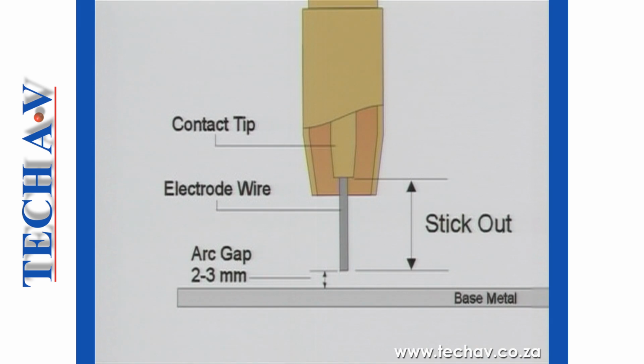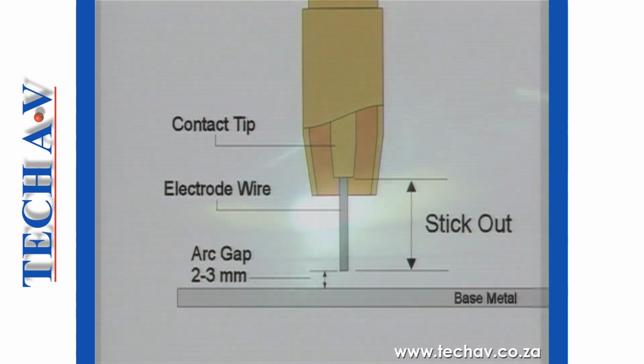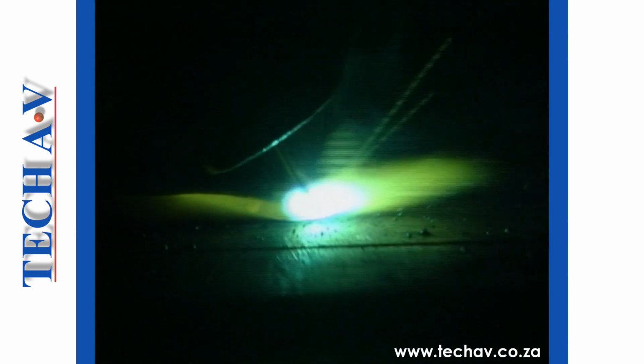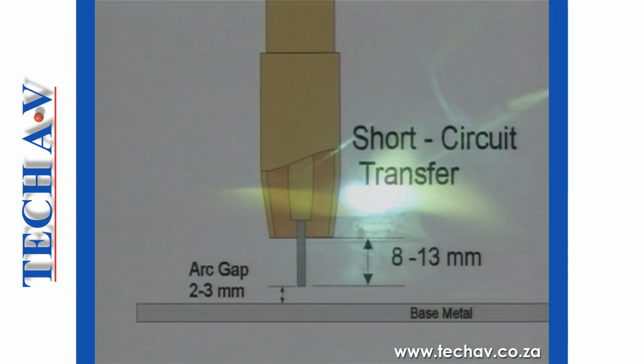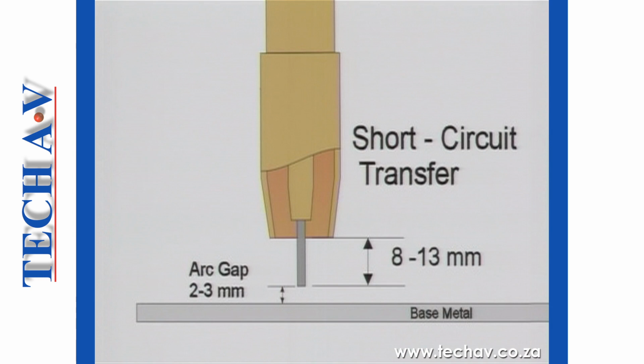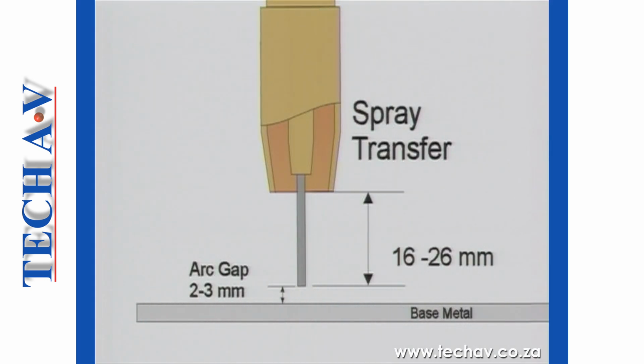Stick-out is the amount of electrode wire that should protrude from the contact tip. This distance is important as it provides the correct conditions in which the electrode wire is preheated, and it also produces the desired envelope of shielding gas over the weld pool. When using short-circuit transfer mode, the electrode should stick out beyond the nozzle by approximately 8 to 13 millimeters. For spray transfer mode, the stick-out should be twice this distance, that is, between 16 and 26 millimeters.